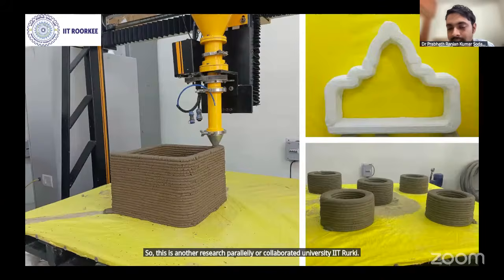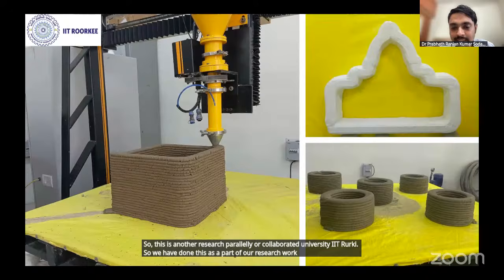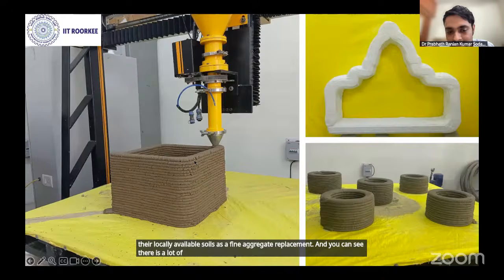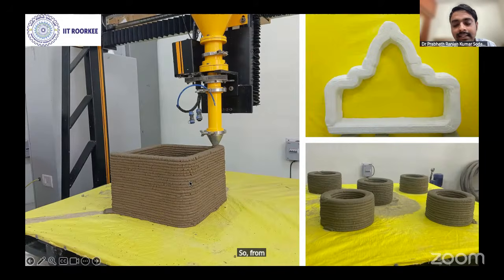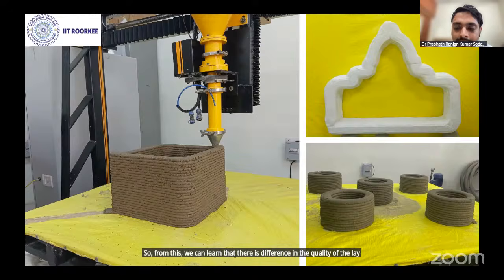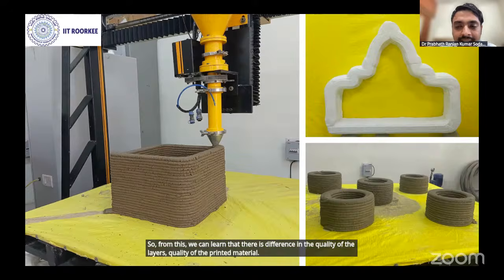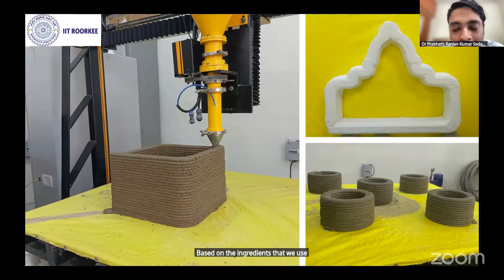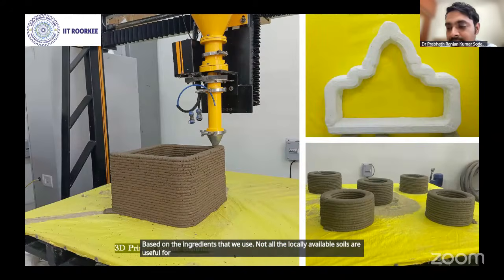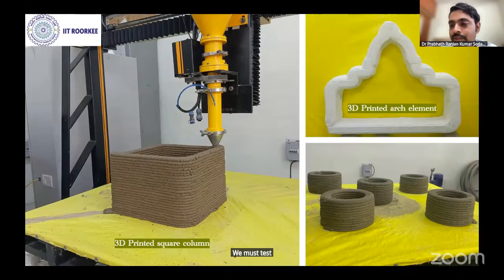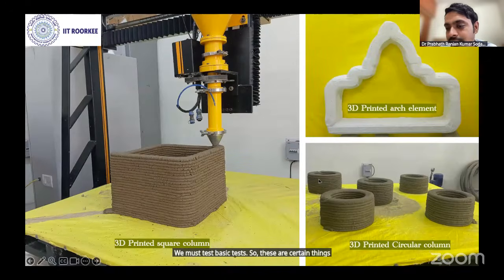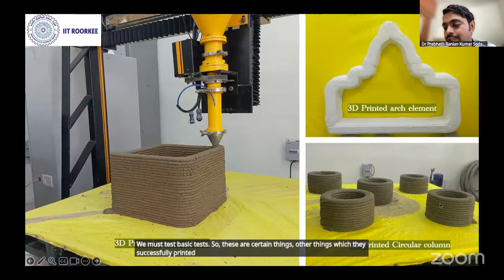We have done this as a part of our research work. They explored using their locally available soils as a fine aggregate replacement. And you can see there are a lot of discontinuities in the surface and in the quality of the layers. From this, we learn that the quality of the printed material differs based on the ingredients we use. Not all locally available soils are useful for printing. We must do basic tests. These are other things which they successfully printed with a good extrusion quality of the layers.